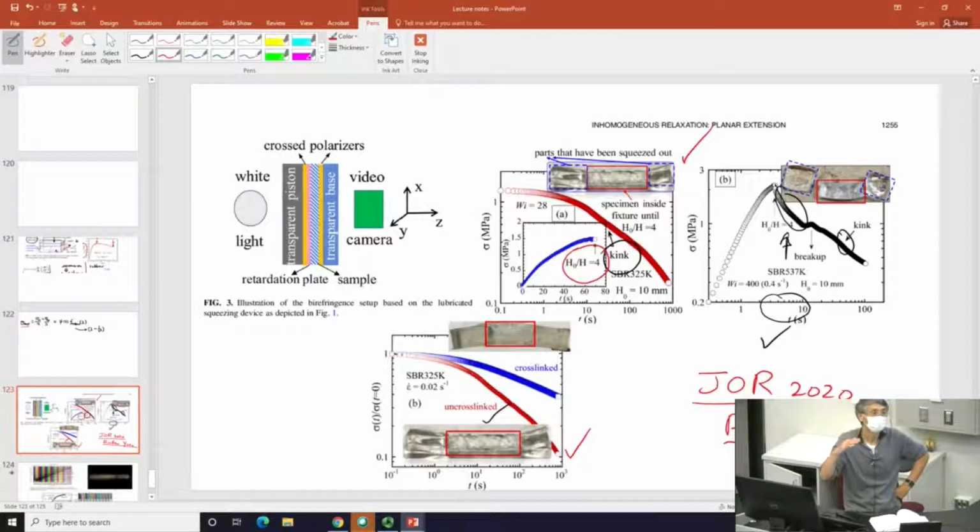And lastly, what about if you waited forever and then lift? Would that be smooth? It will be, if you give an infinite amount of chain diffusion, everything eventually will be uniformly relaxed. In other words, even if you have the wrinkle, which did happen at 100 seconds, let's say that's a fraction of tau, but if you gave 20 taus, all these different cases will swim back into a case where every chain is homogeneous. And when you lift that, of course, it's going to be a smooth sample. Right? So these are just sort of controls showing that there is this wrinkle that is peculiar.